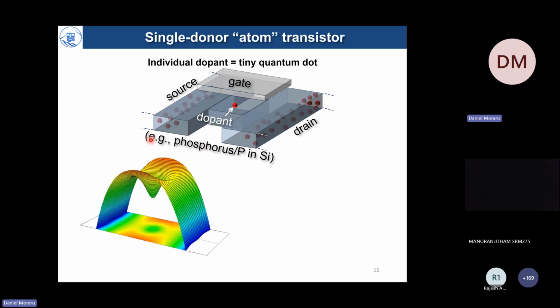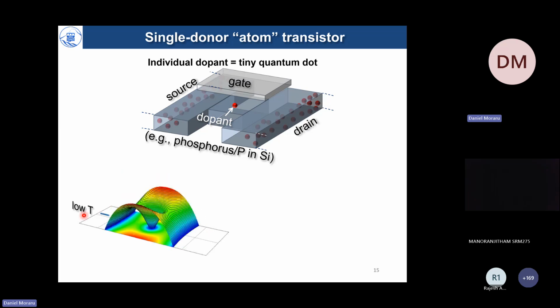We can actually utilize the Coulombic potential well of this donor as a stepping stone between source and drain in this potential map. If you use the gate voltage, you can tune this potential well and bring it in the way of the electrons in the reservoirs, and at low temperatures, electrons would tunnel into this potential well, one electron, and then tunnel out, forming the current. While the electron is inside, another electron cannot come into the potential well because of the electron-electron repulsion force. In other words, Coulomb blockade.